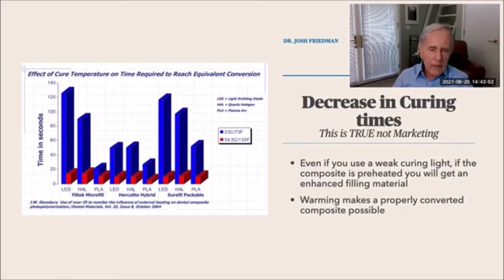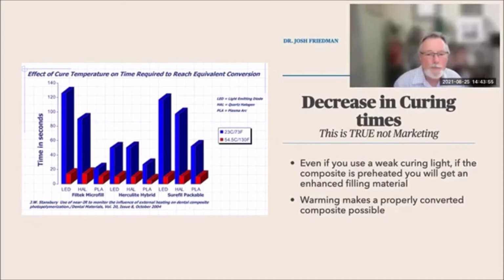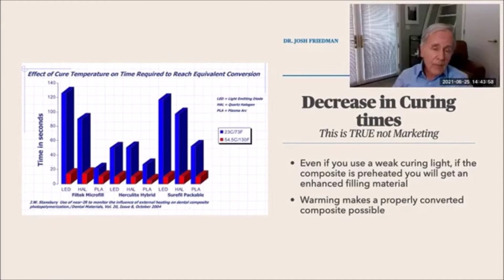light. If you're worried about the intensity of your light, and they vary all over. There was a study years back where we looked at lights throughout a large population in Texas, and they found a huge difference between one office to another. And we see that even in universities. A close friend of mine who teaches at another university went around, tested the lights at the clinic and found differences. So the point is that instead of just trying to have the most powerful light, you should really be thinking about warming the material, and that will have other advantages as you'll see later, but eliminate the need for worrying about your light and know that you're getting a properly converted composite.